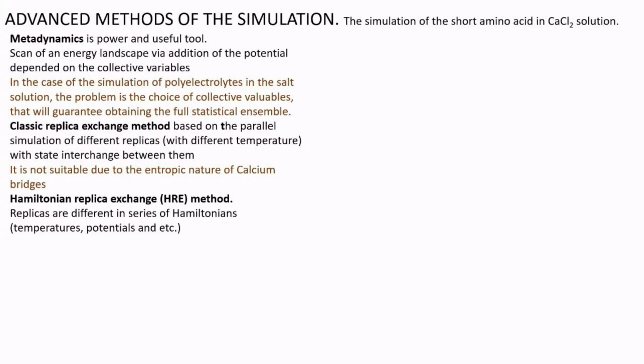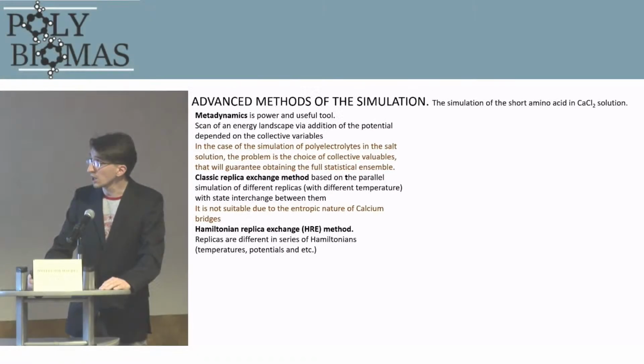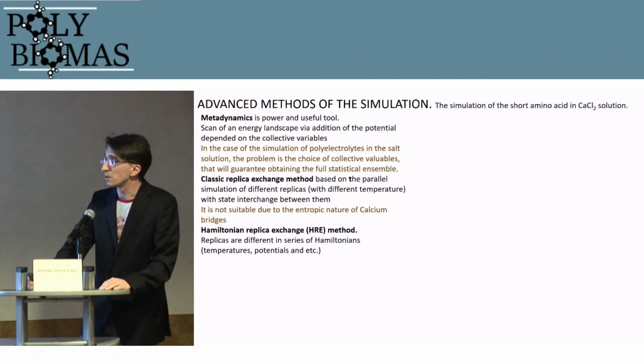Another method is very common and very powerful: replica exchange. When you simulate different replicas in parallel, these replicas can exchange states between them. But in the case of simulation of polyelectrolytes and calcium and mineral ions, the problem is that calcium bridges have an entropic nature, and an increase in temperature does not lead to their destruction, so at higher temperatures the problem of sampling is there too, so we cannot use this method.